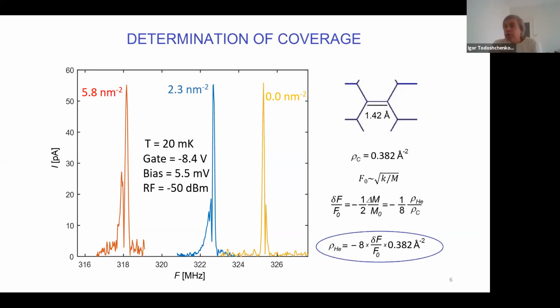So how do we measure the coverage, the density of helium adsorbed on the nanotube? We used the value of the shift of the central resonance with respect to the vacuum one. And we measured this in the liquid, where we did not see any stiffness effect from the helium, but only additional mass, which we measure. So then everything is really known. This is the relative change of the frequency with respect to the vacuum. If we neglect the stiffness in the liquid phase, then it's just proportional to the relative mass change. And here comes the density of helium, which we want to know, and the known density of carbon. So this is the formula that was used to measure the density of adsorbed helium.